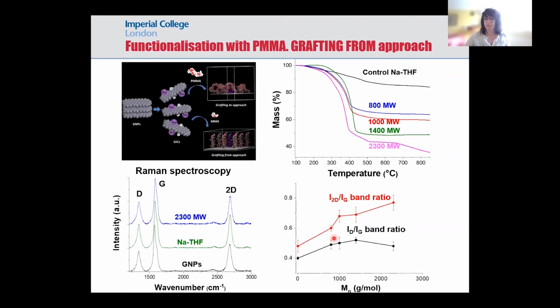And looking at the 2D to G ratios, this ratio gives us an indication of exfoliation. As the ratio increases, we observe an increase in exfoliation. We also were able to see that as we increase the polymer molecular weight, we observe an increase in the 2D to G ratio, meaning a better exfoliation, probably because these chains are separating the graphene layers more efficiently.